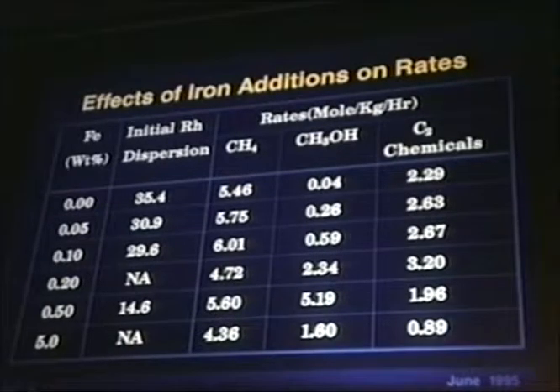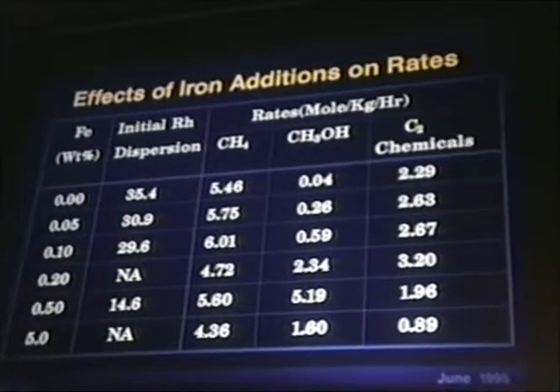The source of iron, of course, is from the stainless steel material of construction used for the autoclave studies, and very likely coming is iron carbonyl formed in the inlet piping leading to the autoclave as a result of carbon monoxide attack on the stainless steel. The discovery of the rhodium-iron system led us to investigate several other mixed metal systems, and certainly noteworthy was the rhodium-manganese, on which we have published, and is the one that gave an order of magnitude higher rates to C2 chemicals.